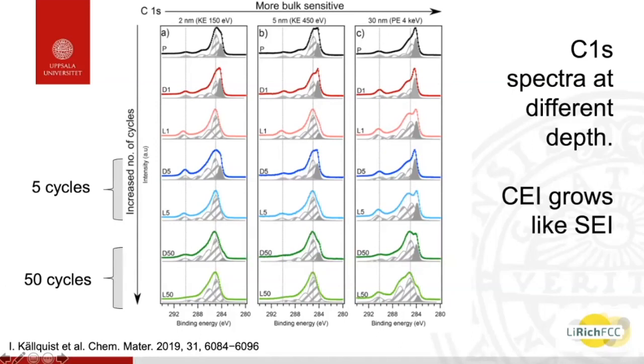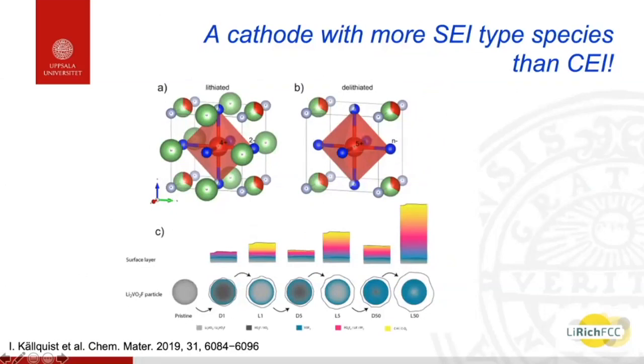So just by having these kinds of reactions going on in the material, we can induce extra reactions in the electrolyte, which leads to these thicknesses. This is just in schematics what we think is happening. And you can see that it's also quite dynamic. From discharge to charge, you actually grow this layer thicker and thicker, but it thins out also. So we can see that we have some redox activity, but it's probably anionic redox activity. I also have other spectroscopic data as evidence for that, but you can read that in the paper.